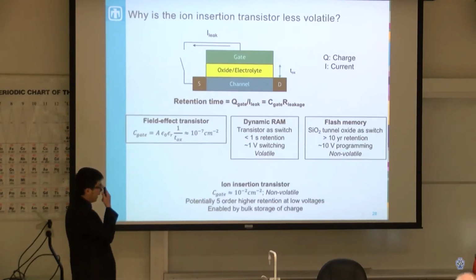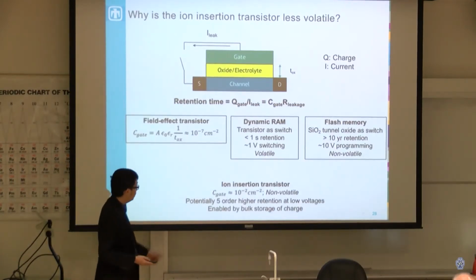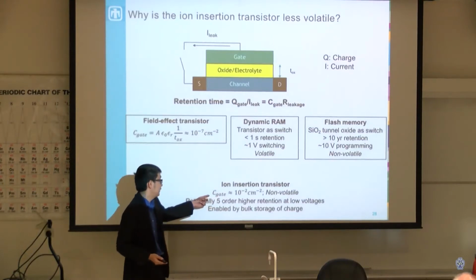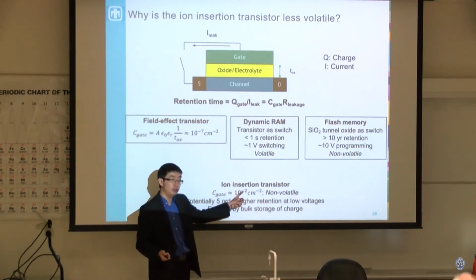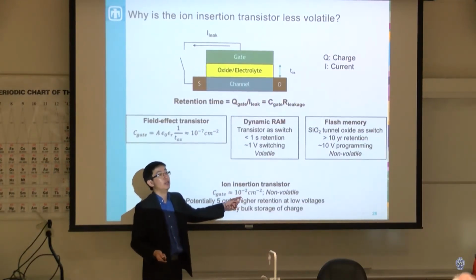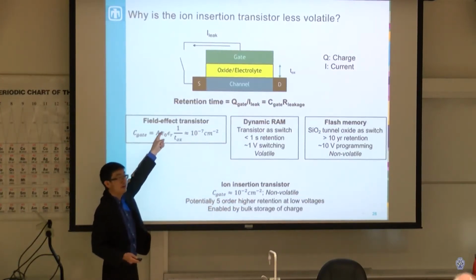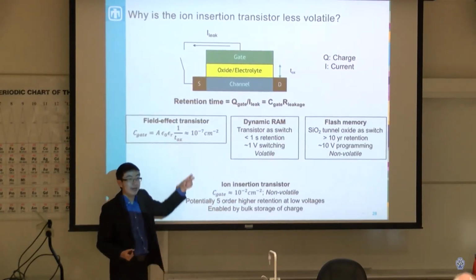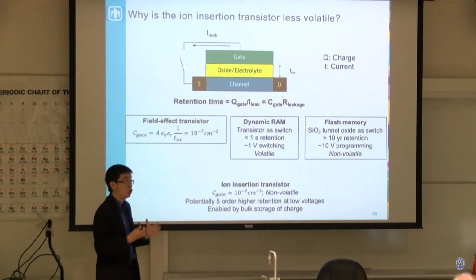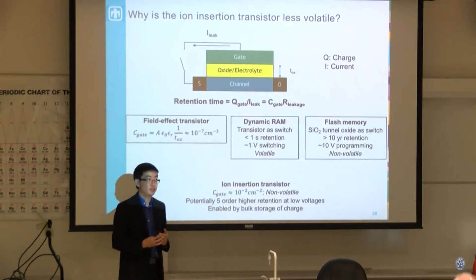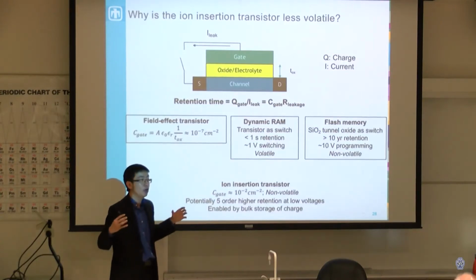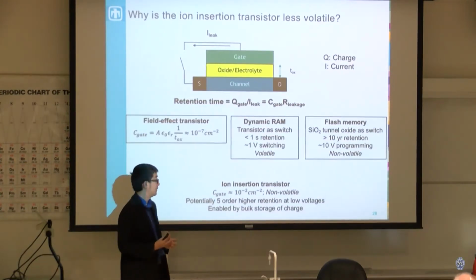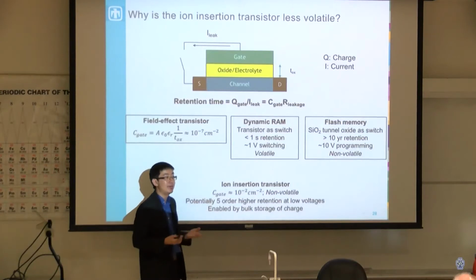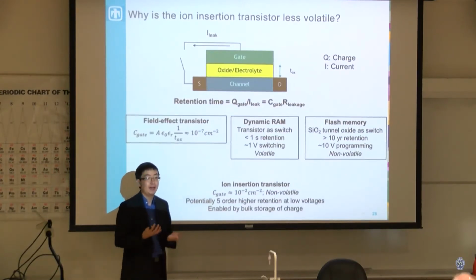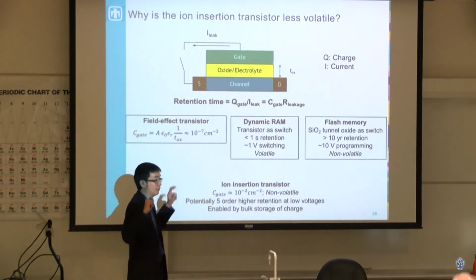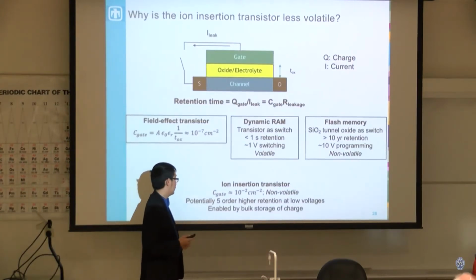What we're able to do with the ion insertion transistor is that we're able to really increase the capacitance, on the order of 10 to the minus 2 farads per centimeter squared. So 5 orders of magnitude higher than a standard field effect transistor. And that results because we can put a lot of charge into our material. We don't have electrostatic buildup, and we're also able to put charge in the entire bulk of the material. So this is assuming, say, 100 nanometers of thickness. Depending on how thick your material is, this effective, quote-unquote, areal capacitance will start to matter.